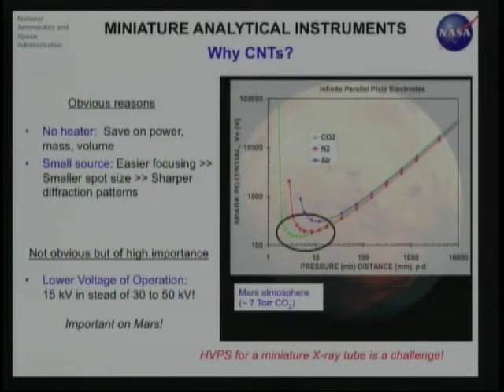In the case of the 28 kilovolt power supply that is flying, we had to use a very exotic dielectric material, sulfur hexafluoride. You can potentially avoid that if you're able to operate the equipment or instrument at a lower acceleration voltage, and with carbon nanotubes, you can operate at 15 kilovolts, for example. I'll show you an example of that.